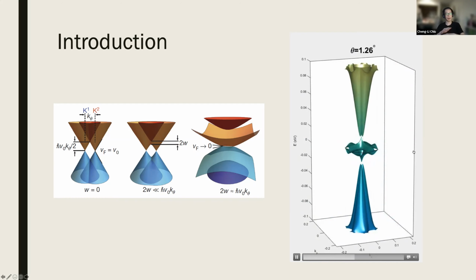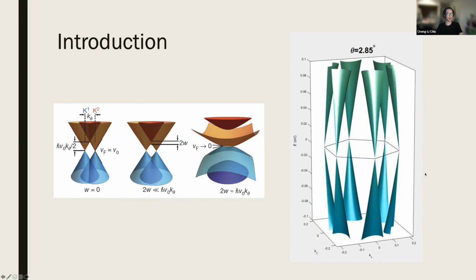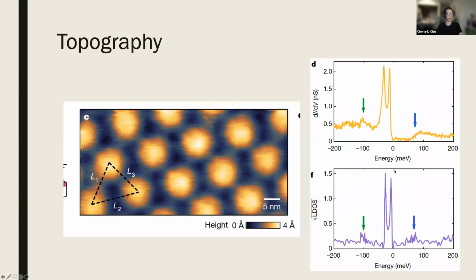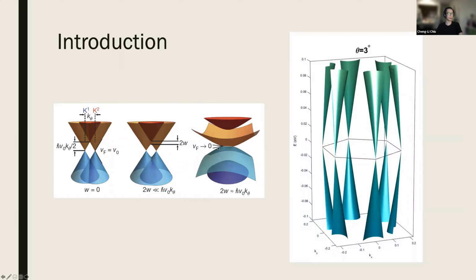What the flat band does is make the electrons very close to each other, so they interact more strongly and create more interaction effects. So this is one of the devices that gives some good data, and you can see there's a Moiré pattern. From this distance, we can calculate the angle, and this is the density of states. Compared with the theoretical calculation, we see that these two sharp peaks are exactly the flat bands shown here.